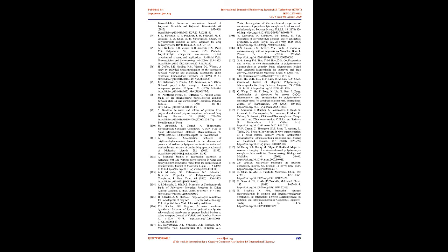114. PECs as diagnostic and imaging agent. PECs formed by grafting chitosan with gadolinium, GD/diethylenetriamine pentaacetic acid, DTPA, were developed by Huang et al. 115. About 300 nm-sized particles were produced when chitosan was complexed with dextran sulfate, electrostatically. In other ways, GD was trapped ionically within PECs with gadolinium chloride, GdCl3. From these two approaches, three types of particles were obtained, viz. GD-loaded, GD-DTPA conjugated, and PECs consisting of both ionically trapped GD and GD-DTPA grafts.